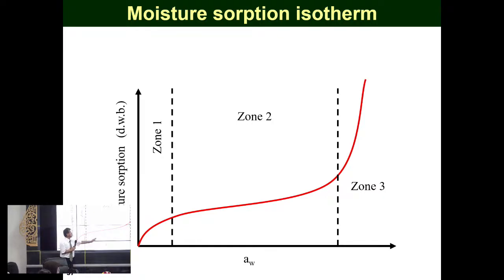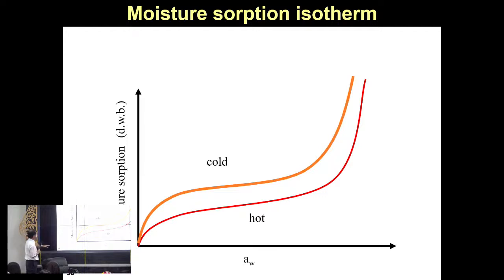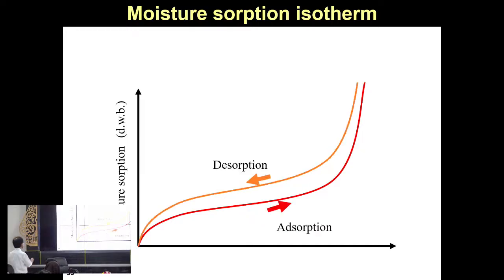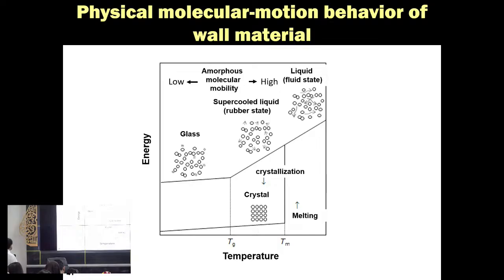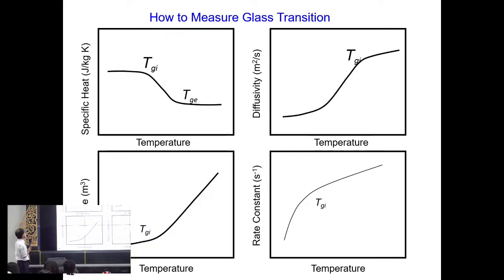In zone 1, zone 2, zone 3, zone 3 is where the powder is very unstable. And then when we get this kind of hot and cold temperature history, or relative humidity history, it is important. So when we think about the molecular scale phenomena, this is a food or some kind of compound, energy against temperature on the x-axis. The glass state energy is almost the same, and then the slope changes. This is the glass transition temperature. But how do we measure the glass transition temperature?